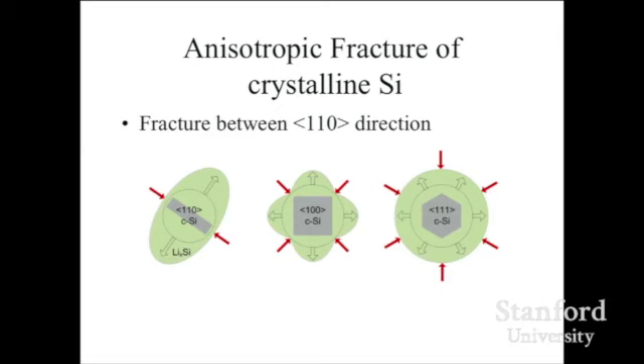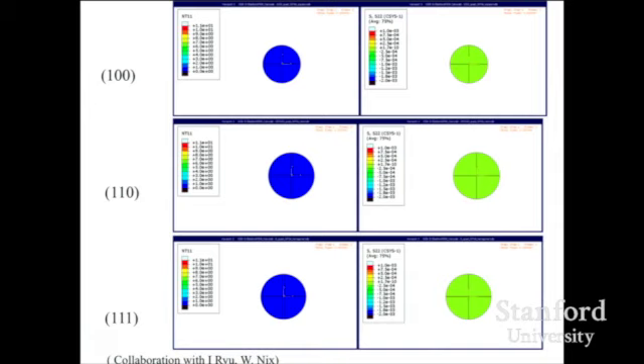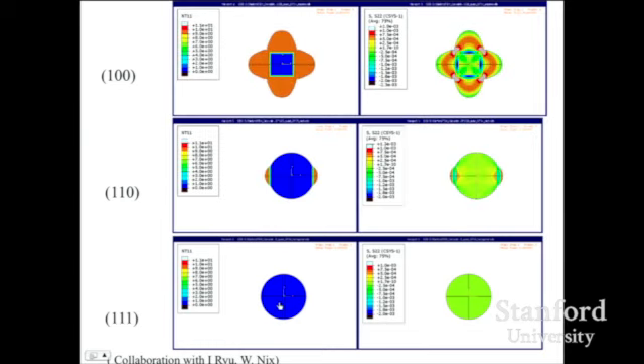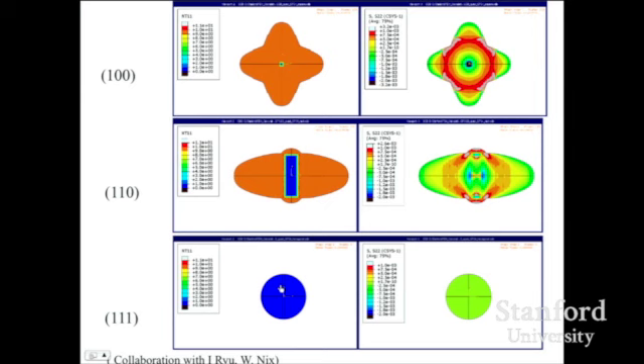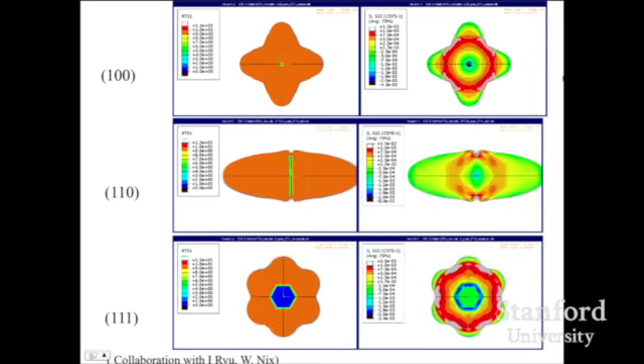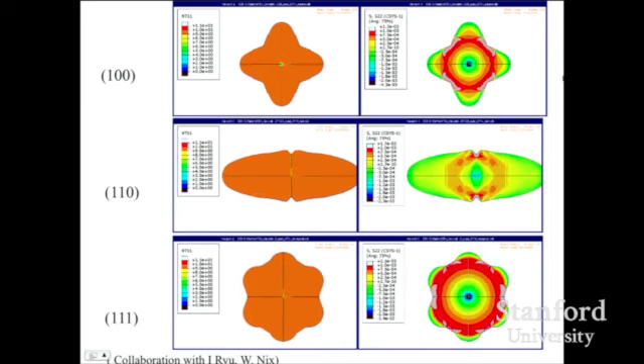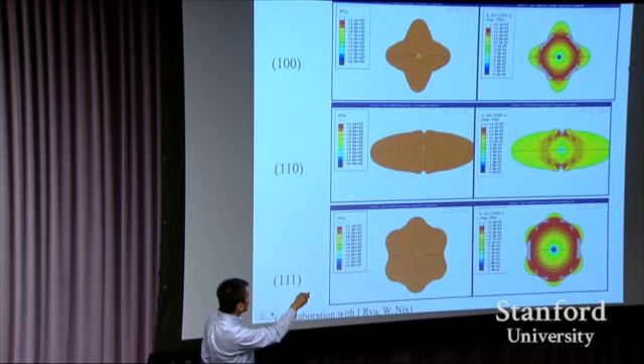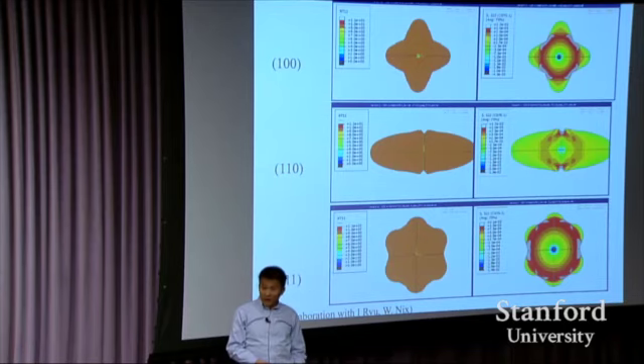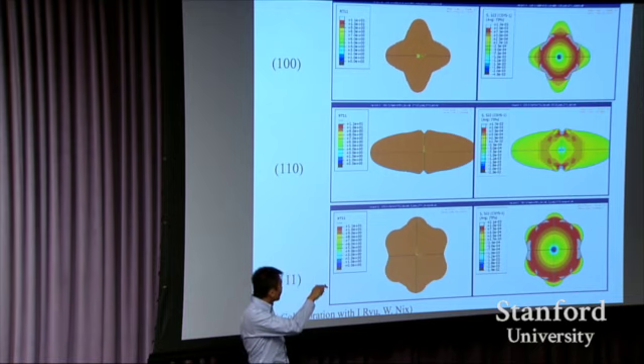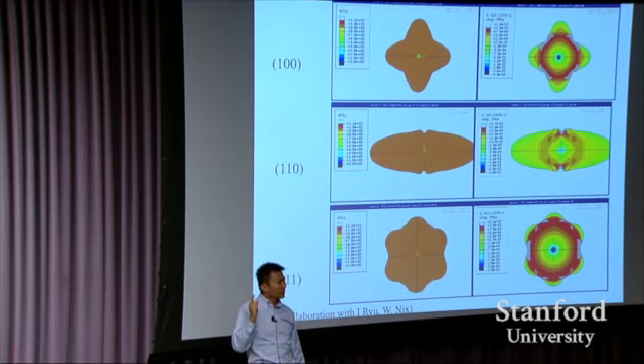So this expansion is really interesting. I'm going to skip through this very quickly. But what I want to show you is that this anisotropic volume expansion has a significant meaning right here. This is a simulation done in Bill Nix's group. You look at this anisotropic expansion and look at the stress profile. The stress really concentrates between the two expansion directions. That's the tensile stress right there. That's exactly where the breaking happens. So the breaking doesn't happen in a random position. It happens in a fixed position.